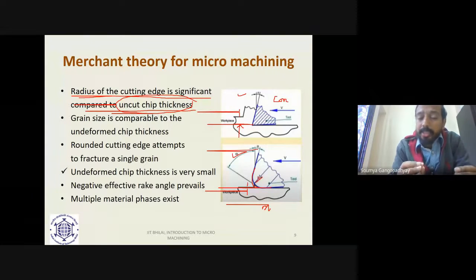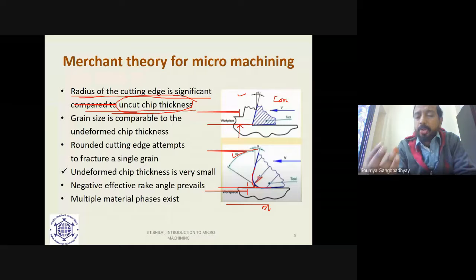But then why is it considered sharp by Merchant? Because the uncut chip thickness is hundreds of microns. If the edge radius of the macro cutting tool is 10 micron, then the uncut chip thickness is 300 micron, 400 micron, 500 micron. You see that there is an order difference between the edge radius and the uncut chip thickness. But in micro cutting, they are of the same order of magnitude. Now, what is the implication in terms of mechanics when the cutting edge radius and the uncut chip thickness become of the same order of magnitude?